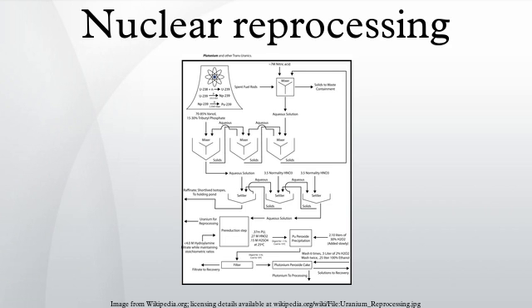The plutonium-uranium ratio in the ash may even approximate the composition needed for fast neutron reactor fuel. Further fluorination of the ash can remove all the uranium, neptunium, and plutonium as volatile fluorides. However, some other minor actinides may not form volatile fluorides and instead remain with the alkaline fission products. Some noble metals may not form fluorides at all, but remain in metallic form. However, ruthenium hexafluoride is relatively stable and volatile.